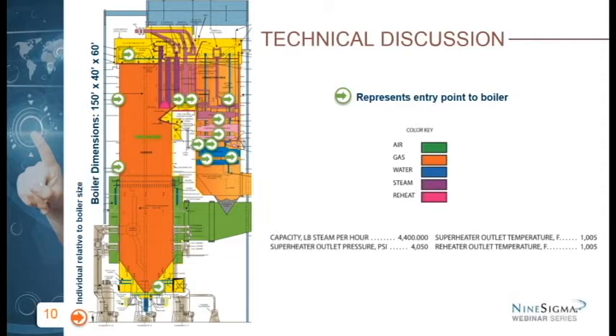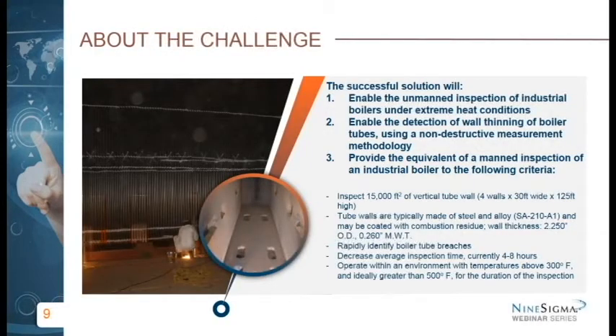And maybe if we could just go back one slide. Wanted to point out one thing. What you see here in this picture is a person working on what we call the tubes. And tubes is a little bit misleading. These are really pieces of pipe. They're about 2.25 inches in diameter, and the thickness of the wall is usually greater than 1/4 inch. You see in the second bullet point there under item 3, that 0.260 inches of MWT, that means min wall thickness. So typically these thicknesses are greater than that. We will go in and replace the tubes if they get lower than that 0.260.